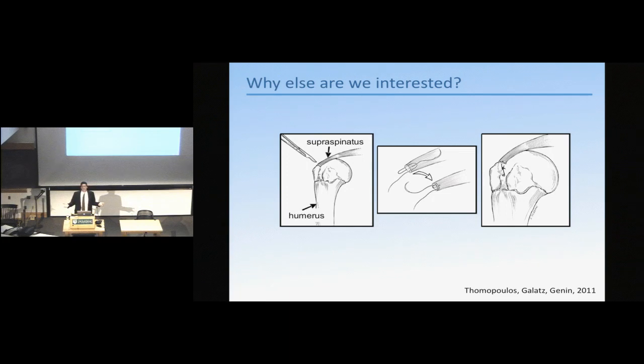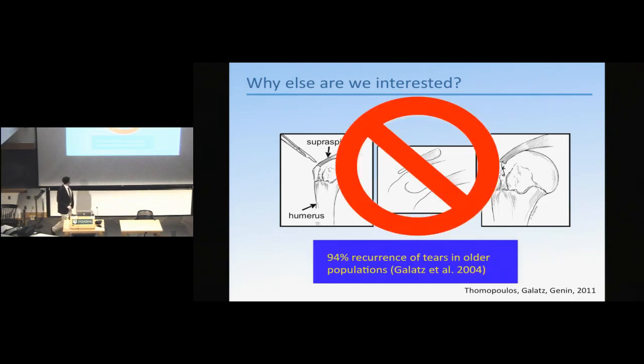Now, there are a lot of engineers in the room who have experience in mechanical design, and this should violate your intuition. If you see something like this, you think it would fail 5 times out of 100. But your intuition would be wrong. The failure rate is actually 94 times out of 100 in the older populations, and in the 20 to 45% range for younger populations. We believe that these high failure rates are due to the just complete ignoring of this engineering problem of biomaterial attachment in surgical procedures.